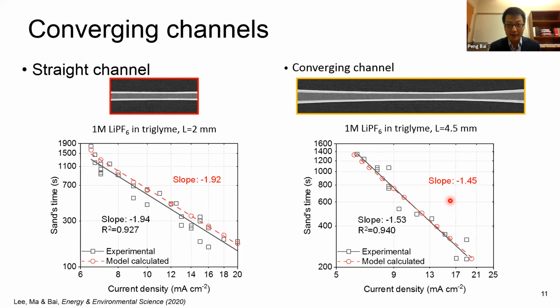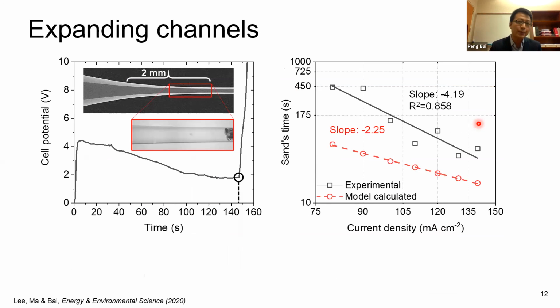And what's surprising though is that visually, you would see that this change of curvature is very tiny, right? So that means the transport dynamics, the penetration process, is very sensitive to the geometry. So here, we further tested: if we push the metal electrode to the other end of the tapering part, so that we have an expanding channel, what will happen? And this is what happened. Not only do we no longer have the slowly climbing voltage and then the divergence, but we have a decaying voltage, then the divergence of the voltage. And what's more surprising is that now we have a slope with a negatively deviated exponent. You can see here, -4. Initially, the ideal case is -2. Now we got -4.